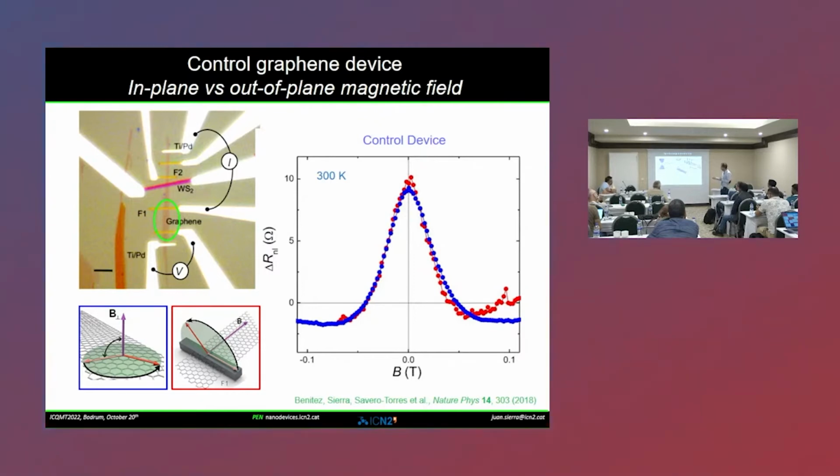If you remember what I explained previously, here we have an in-plane spin texture in the structure of graphene. So if now I run a current in this direction, I will shift these states and I will create a spin density in plane in a direction that is transversal to the electric field.